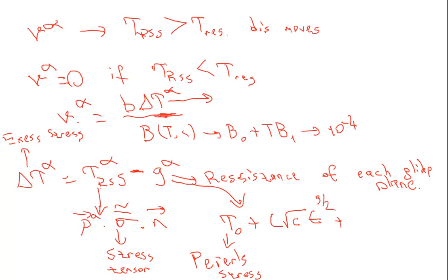Grain boundary hardening, right? It is related to the mean free path of dislocation, and precipitation hardening, which is L minus 2R. Then you need to add all sorts of hardening. Of course, the strain hardening can be calculated through alpha mu b square root of dislocation density. Once we add all of these values, we calculate the resistance of each glide plane.